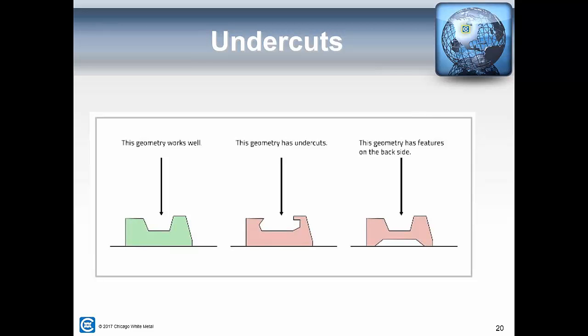The third image on the far right, you'd be able to draft appropriately the top section of it. However, because there's that gap between the casting and the parting line, you would not be able to form that feature. The only way that would work is if you somehow wanted to jog up the parting line either between the 2 cored-out areas or that kind of situation. You have to adjust the parting line in some variation to make that work.